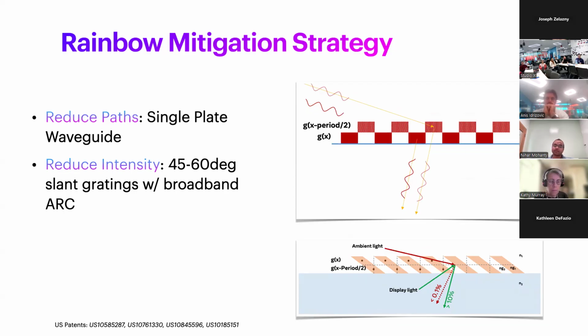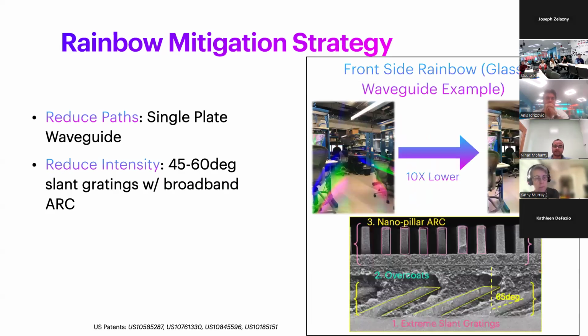Underline, I said some of the rainbow paths. This only works for the front side rainbow. There are two key aspects to this approach. The depth and slant angle of the gratings needs to be within the optimum range, not too deep, not too shallow. And the anti-reflective coating needs to be broadband at wide angles ranging from plus minus 90 degrees.